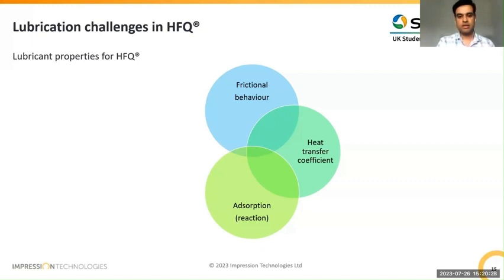And all these aspects are being researched mostly in the EU and in America, but the UK tends to not have much research on sheet metal forming, which is one of the reasons we are trying to introduce this field to us. But more importantly, what is generally lost in research is the cleanability. There is no point in evaluating and trialing a lubricant that is good at friction behavior and heat transfer coefficient and does the job, but cannot be cleaned after the part is formed, because it gives you a lot of surface quality issues. So it's not directly linked to tribology, but Graham and I try to work on formulations which not only give us a good frictional response, but good cleanability as well. Because eventually we want clean parts to be sent for painting.